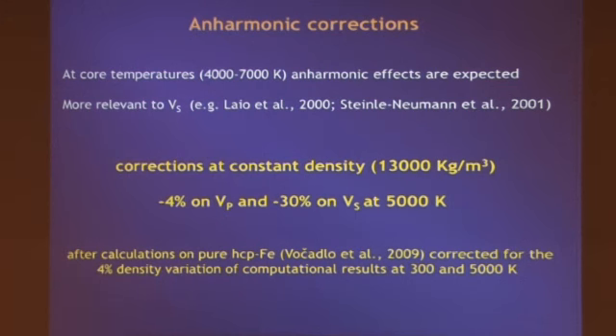As such, we decided to correct our result for an anharmonic correction at a constant density of 13,000 kilogram per cubic meter, taking a 4% softening on VP and 30% softening on VS at 5,000 Kelvin. This correction comes from the work of Vocadlo and co-workers. Probably she's going to speak a bit more in detail of that after a correction for the density variation, because here I just want to look at the anharmonic effect at constant density.